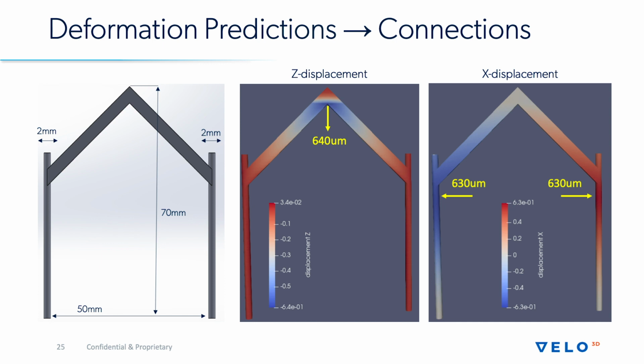In this case, right at the connection point where these planes come together, they actually pull the connection point down by about 640 microns, and at the same time bow out the edge walls by another 630 microns. And so you can see in this case that this would then give indication to the engineer, either do I want to change orientation or change the support strategy on this particular part to try to avoid these types of deformations, or they could use the Velo software to do the pre-object deformation, which would allow them then to print the part and have it come out to their correct shape.